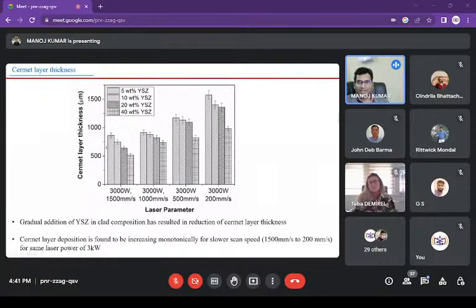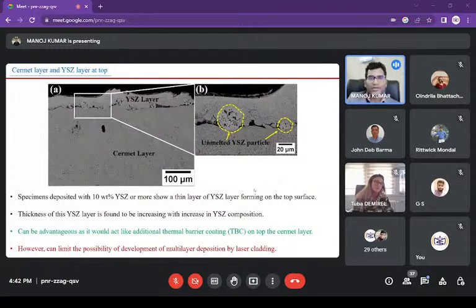At the same time, when we are increasing the YSZ component, I mean the oxide composition in the clad powder, the thickness of the clad is reducing. So this is one of the key points we understood from this experiment. Another key point we could observe here is that when we deposit a significant amount of oxide, not all the oxide goes into the clad zone, forming the cermet layer. However, some of this YSZ powder gets deposited on the top surface.